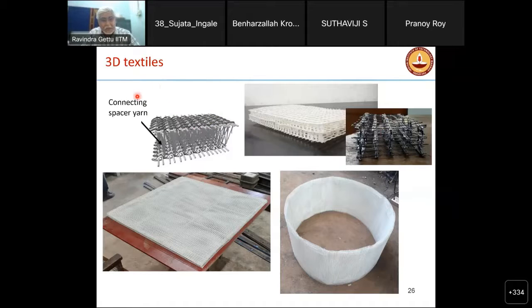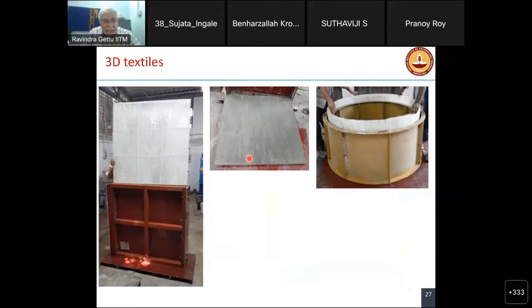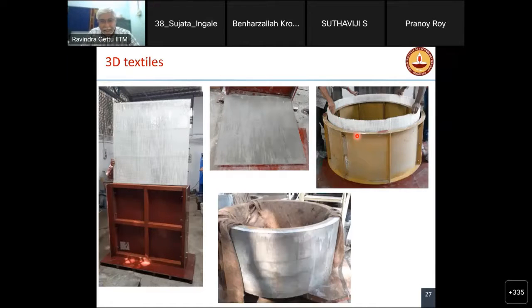So we think the future could be with this type of textiles, textile meshes, which can be prefabricated and put into practice. So this is how it's done. You have a 3D textile, not layer by layer laying up, and then you insert it into the mold, and then you can get the element. Similarly, we are doing it also for a ring. So you can have the reinforcement made, prefabricated, put it in, and then you pour the binder inside to get your element, and you get something that is very neatly done. And we can use this for different elements. Here we are using it for tanks, but other things are also possible.